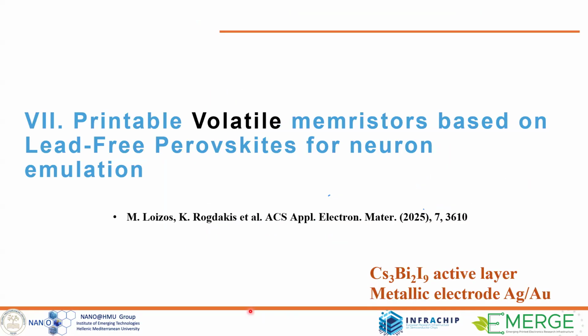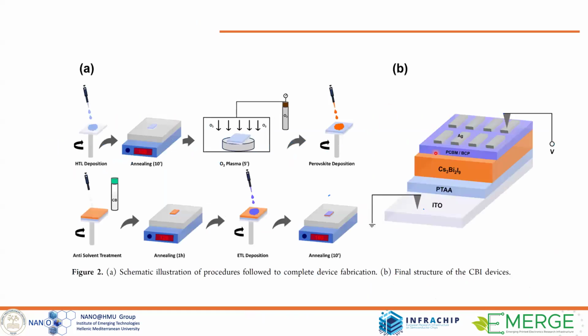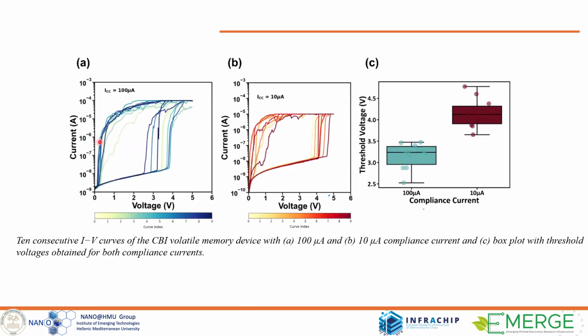In this stoichiometry here, we tested both silver and gold as electrodes. In both systems, we managed to have a volatile memristive behavior, not non-volatile. That was another goal. The manufacturing process is again very, very simple, a typical inverted PIN solar cell structure. These are the standard volatile IV characteristics. You can see that when we remove the bias here, the device always stays at the high resistance state. So this is the volatile type.